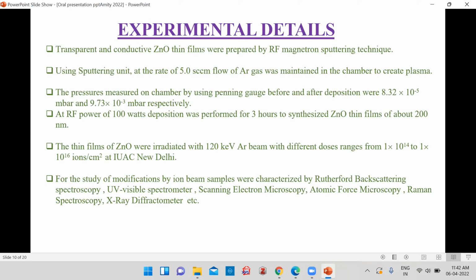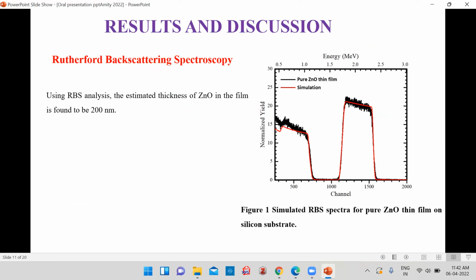These are the results and discussion. First, we have characterized with RBS. This is the simulated RBS spectra for pure ZnO, in which we have simulated the spectra, and the estimated thickness is found to be about 200 nanometer.